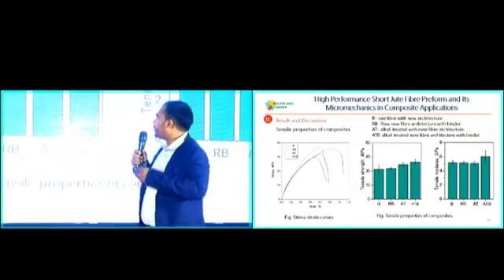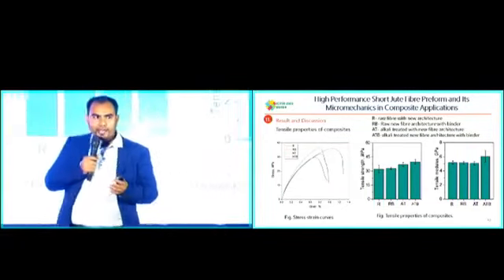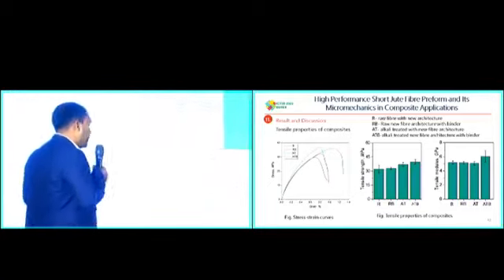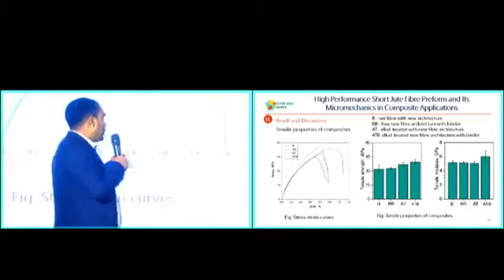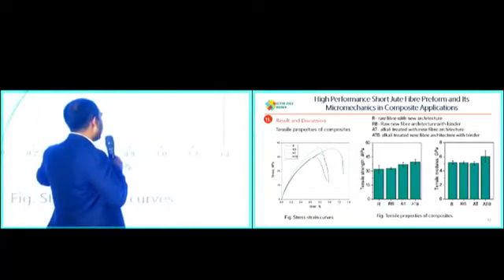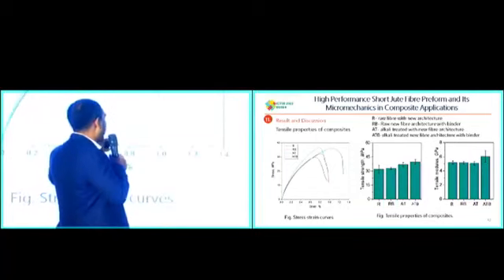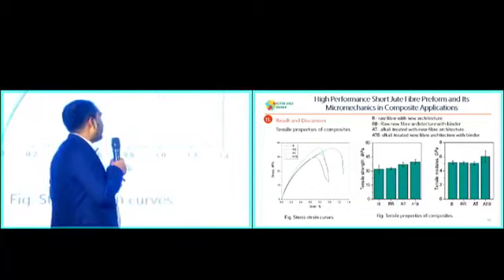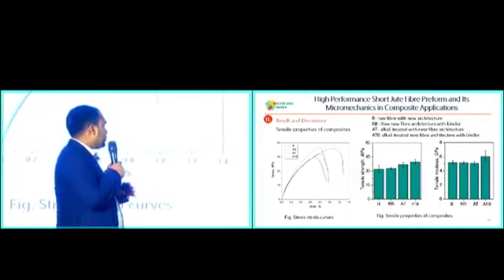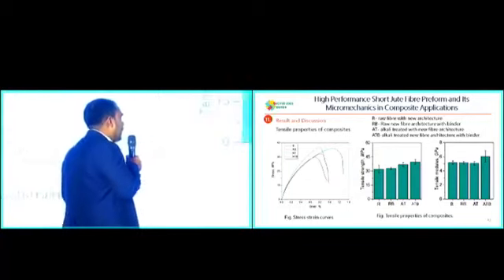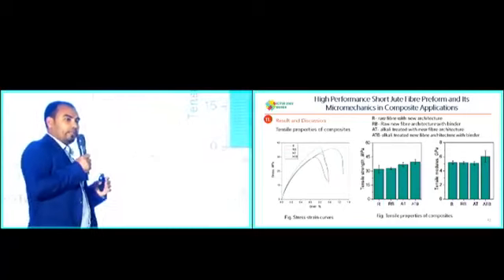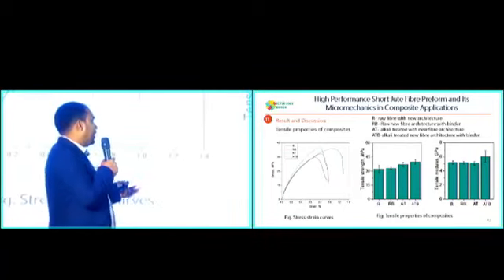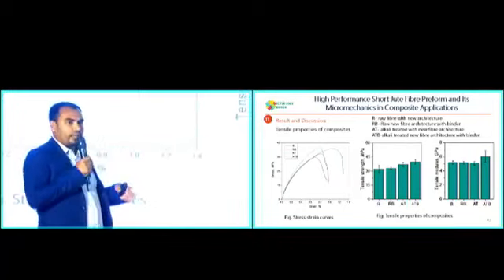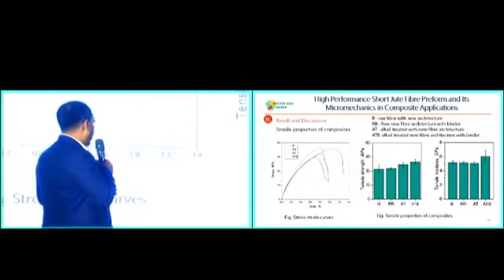It gradually improves when you apply the binder, and also when you apply the alkali treatment. So it is gradually increasing. As you can see from the figure, the tensile strength has increased from 30 to more than 40, 45, something like this. Also the tensile modulus has increased maximum for the ATB, that means the alkali treated architecture with the binder applied. So there is a little bit of improvement of the properties after different kinds of modification.